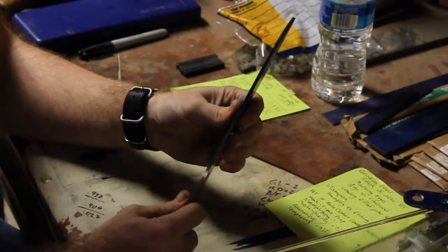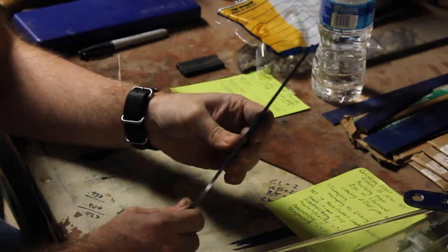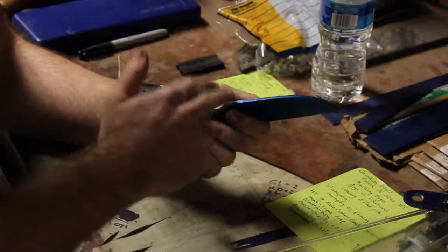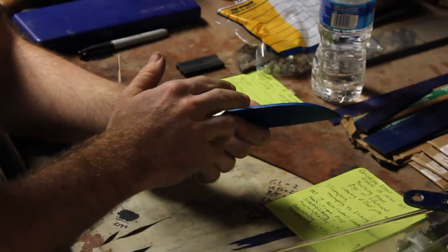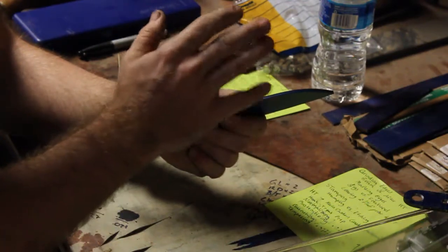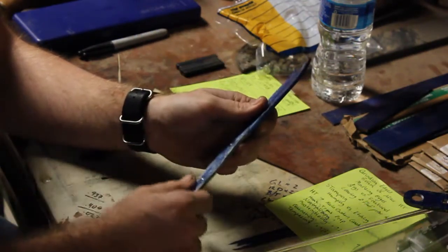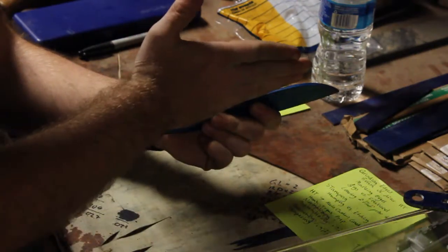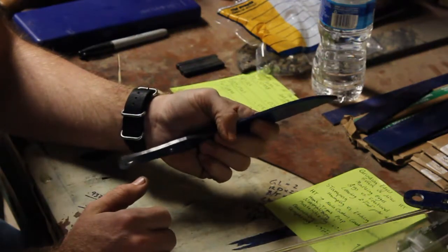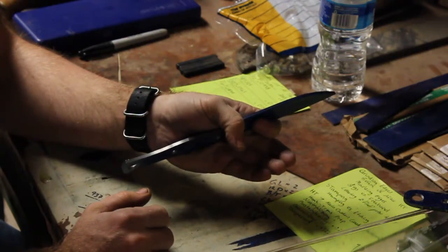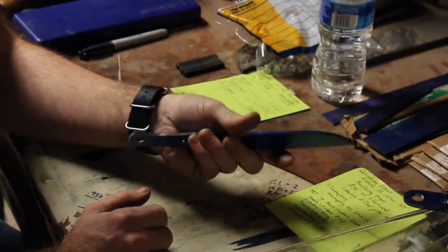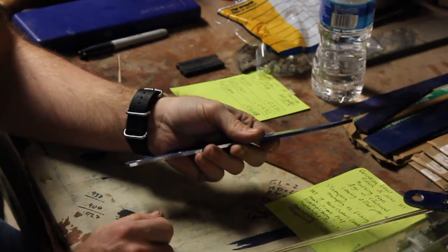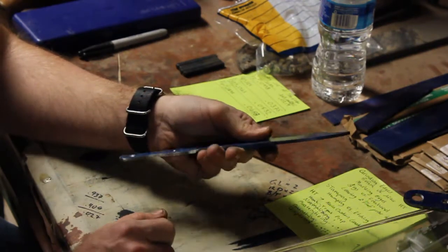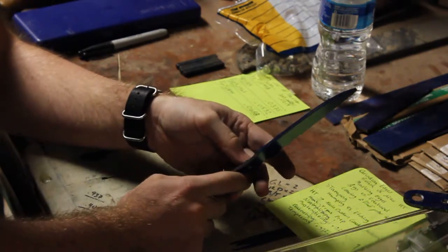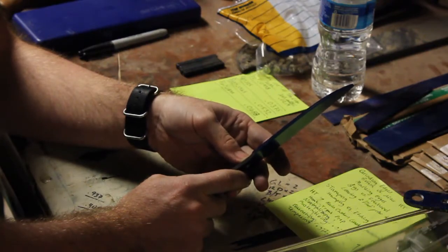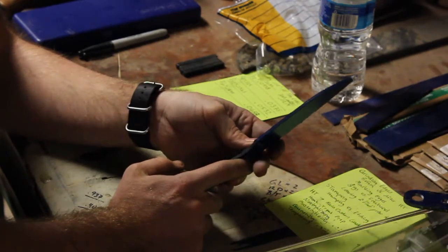So when you grind your edges prior to heat treat, it's important to leave at least several thousandths of an inch flat. I've seen several different numbers on this. I prefer to leave slightly less than a dime's width. I prefer 0.05 inches. I've heard as few as 10 thousandths of an inch.